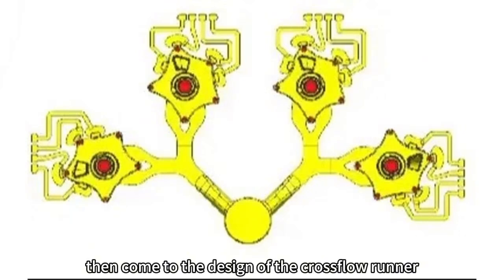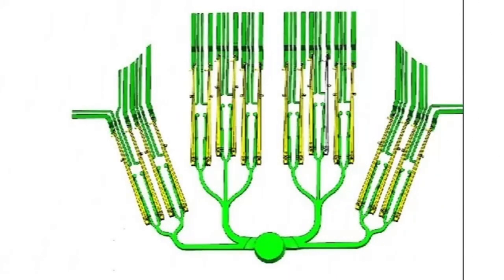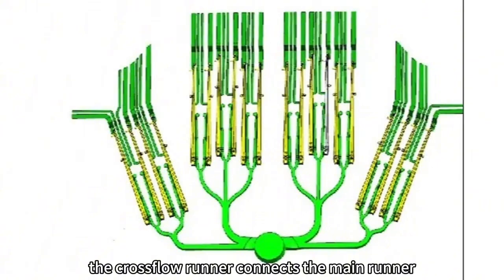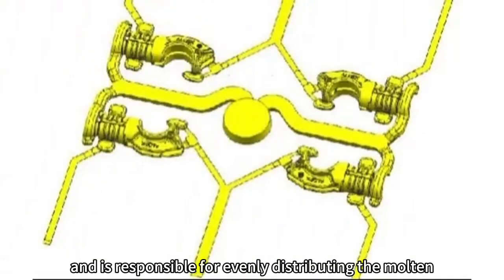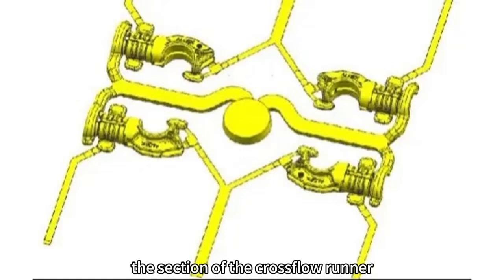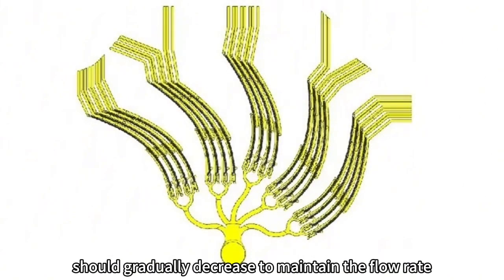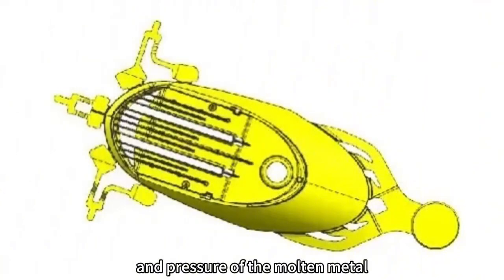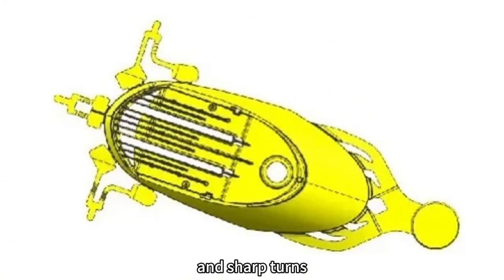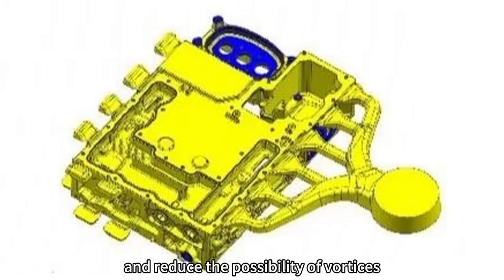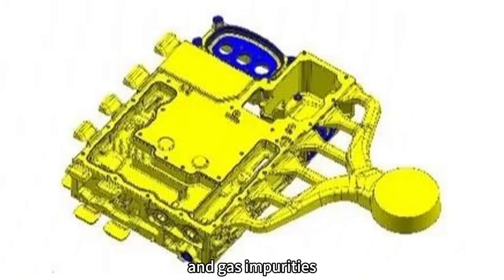solidification. Then come to the design of the cross runner. The cross runner connects the main runner and the inner gate, and is responsible for evenly distributing the molten metal to each inner gate. The section of the cross runner should gradually decrease to maintain the flow rate and pressure of the molten metal. The design of the cross runner should avoid dead corners and sharp turns, and reduce the possibility of vortices and gas impurities.